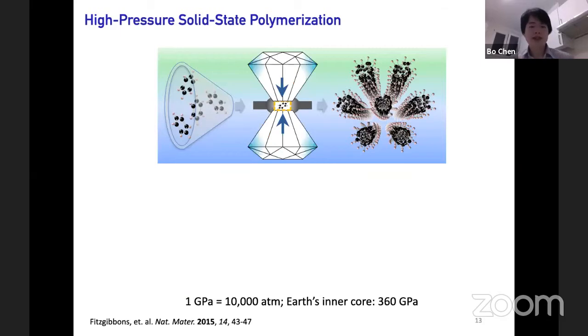Now moving to the synthesis. The actual synthesis of nanothread was done through high-pressure solid-state polymerization. Here I'm showing you a schematic where we can put benzene molecules into this diamond anvil cell under compression, and out comes the ordered nanothread crystal. So a few words on the diamond anvil cell. This is a specially designed apparatus to apply hundreds of gigapascals of pressure to the sample.